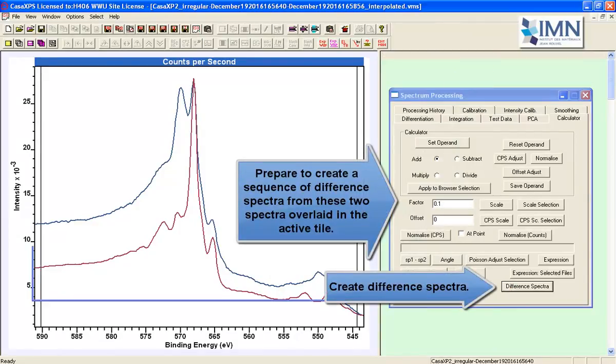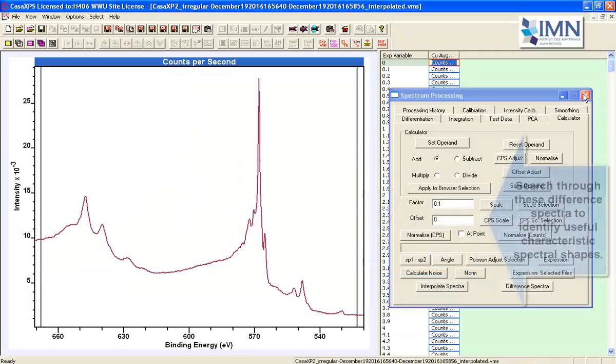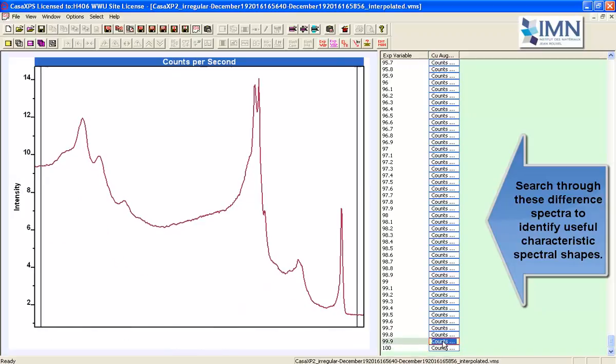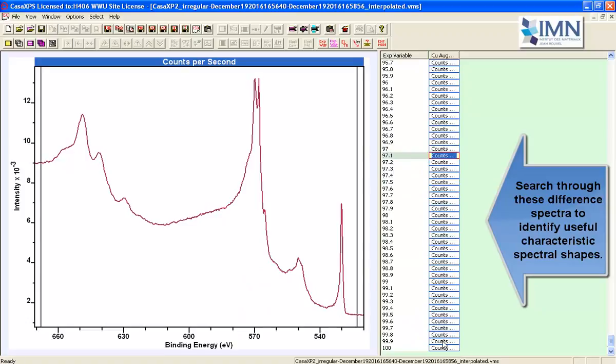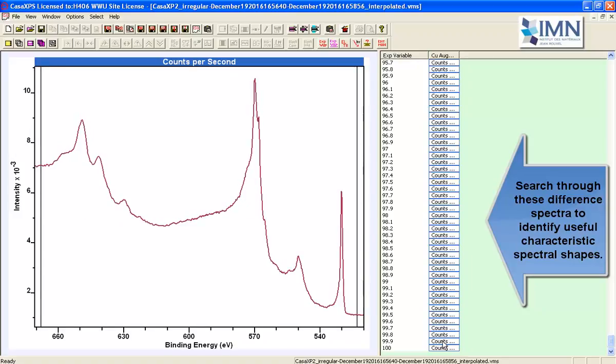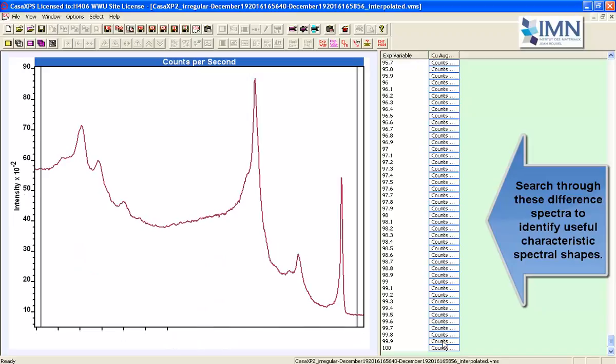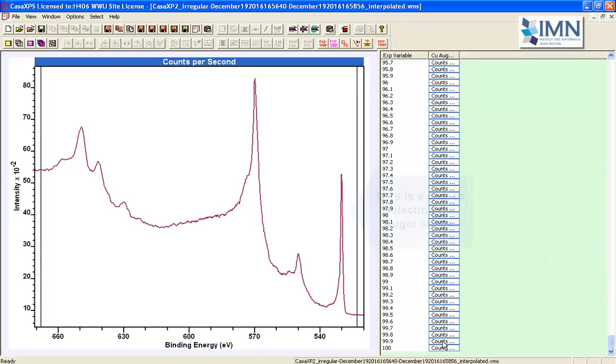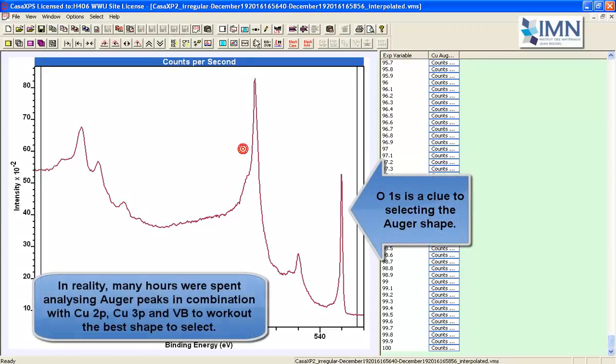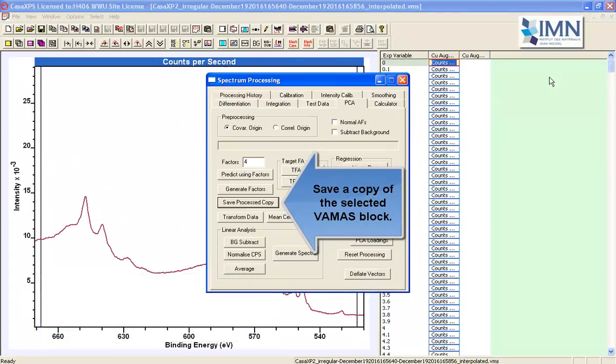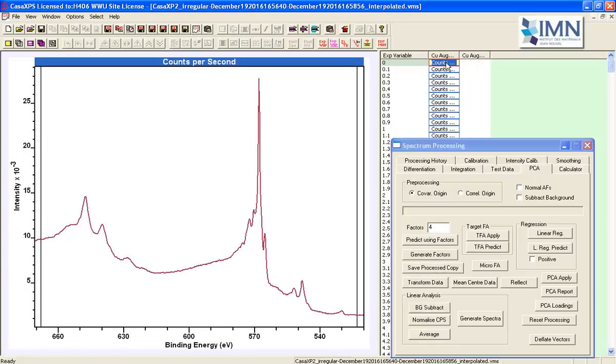Although these data contain different shapes, we're going to use difference spectra to work out more representative shapes for the different oxidation states of copper. We've worked out a sequence of spectra calculated from two spectra in the active tile — they represent a blend and a difference of those blends — so we can step through and look for shapes that enhance or remove the oxygen peak. In this example, we've tried to produce a more pronounced oxygen peak, making it more characteristic of the copper suboxide we anticipate.